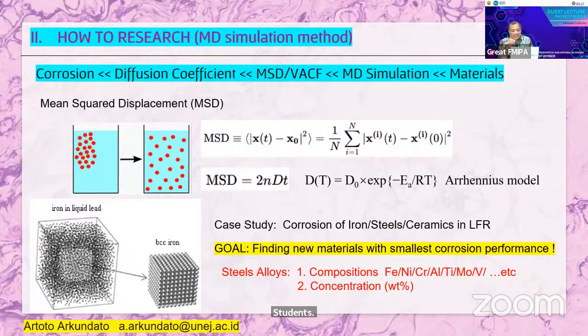For molecular dynamics simulation, we can see this corrosion by calculating what we call MSD, mean square displacement. Mean square displacement is used to learn about the diffusion process, and at the end of the simulation we can calculate the diffusion coefficient. If the diffusion coefficient of steel or iron is lower, then the corrosion is lower. If the diffusion coefficient of iron atoms is higher, then the corrosion is also higher. So in our research, our job is to find a method and material where the diffusion coefficient of iron or steel is as low as possible.